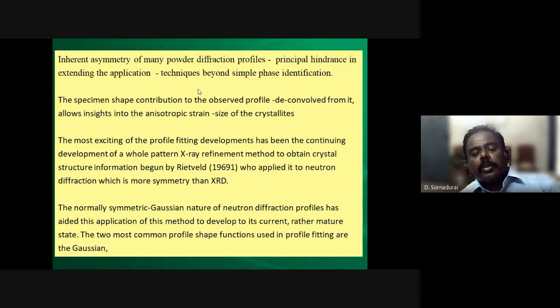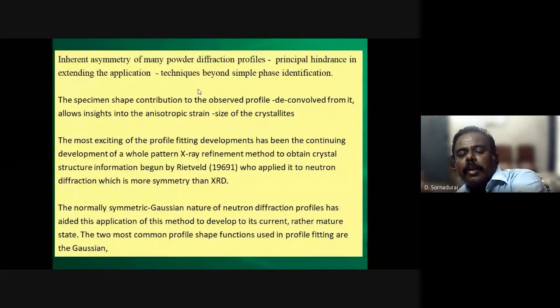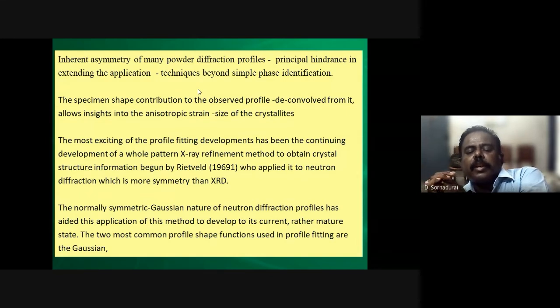Okay, so similarly, the most exciting of the profile fitting developments has been the development of whole pattern X-ray refinement. That is Rietveld refinement, which is a starting point, which can give the percentage of the phases in volume as well as in atomic percentage. From that you can get the volume fraction by Rietveld refinement. You can put up to 8 phases at a time in the fitting, and then you can find the volume fraction of the sample. Okay, what are the phases that exist in the sample? So this was all started by Rietveld.